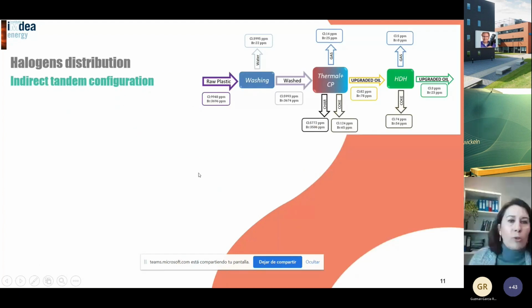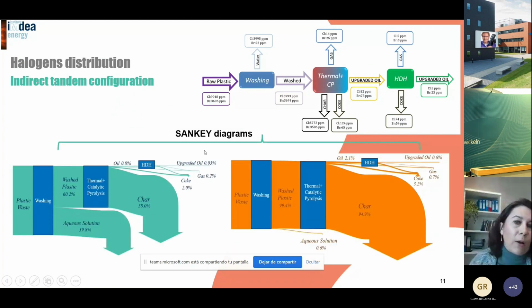Also, we explore the distribution of the halogens in the different fractions, because this is a quite important issue for the viability of this process. And we found that both halogens, chlorine and bromine, were especially accumulated in the char. In the case of chlorine, there is also an important fraction on the aqueous solutions that we employed for the washing of the plastic wastes. But there was just an important thing, a very, very low amount of chlorine in the other fractions.